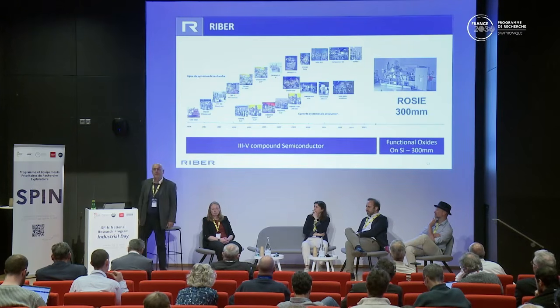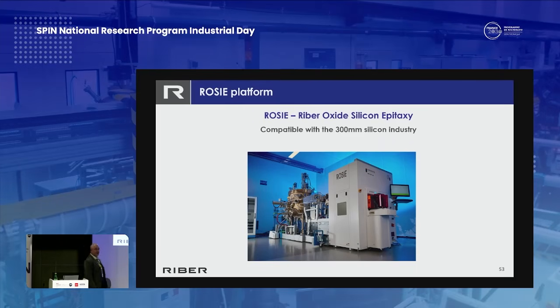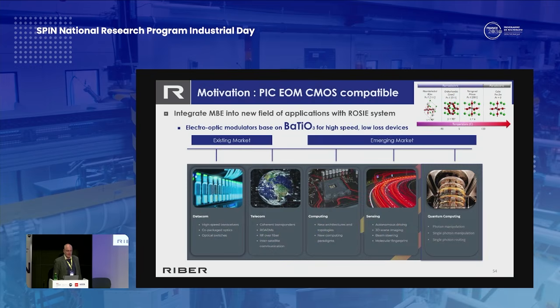And we have developed the ROSIE machine. The ROSIE machine is a 300 millimeter machine, compatible with the silicon industry. Thus, this machine can handle a full cassette of, let's say, 25 wafers in a run. At least, this is the promise of that prototype. That's why Riber goes into the silicon industry with this new kind of material, which is barium titanium oxide. Barium titanium oxide has a unique feature.